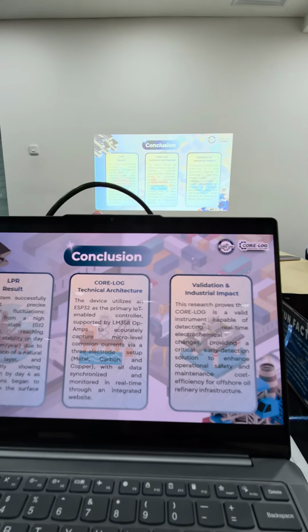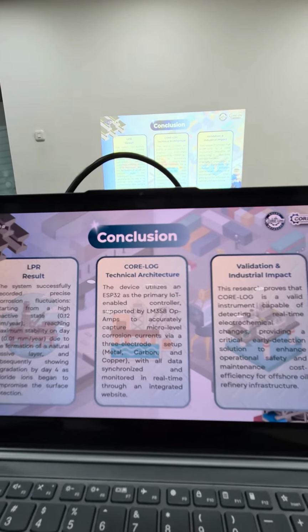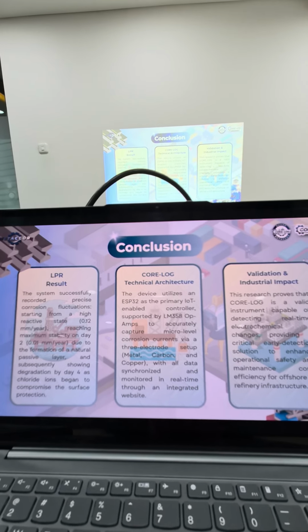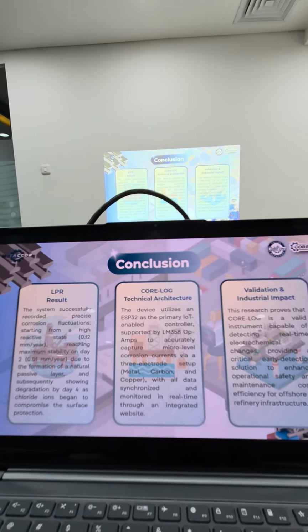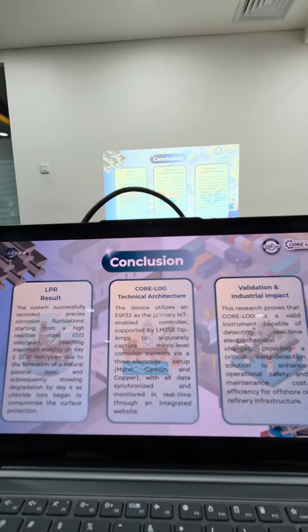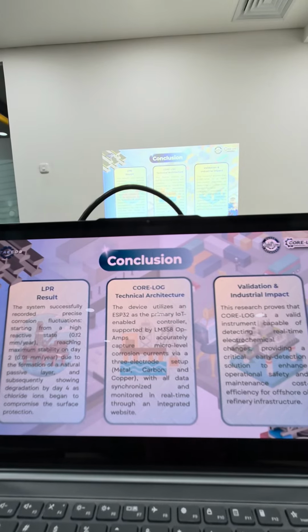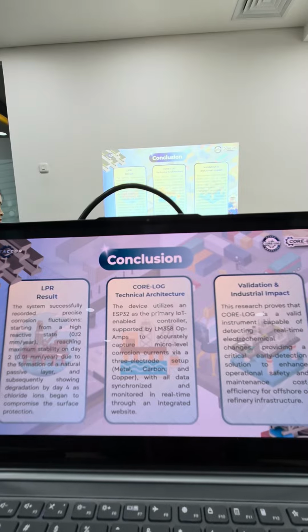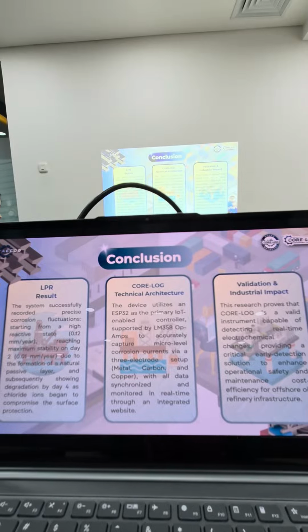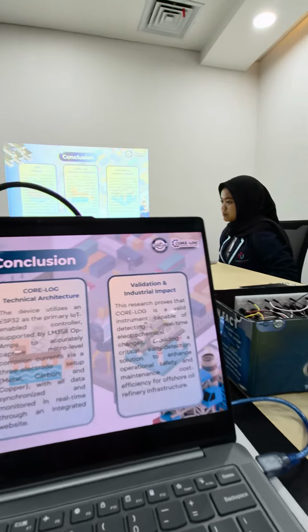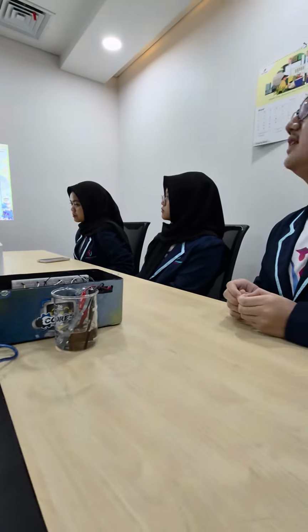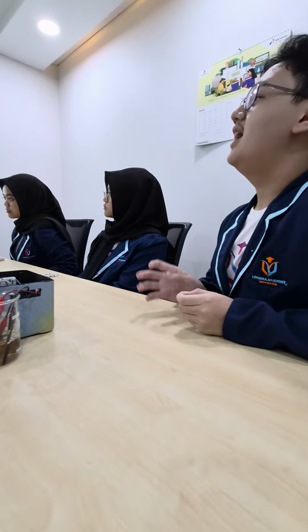The next one, we're going to talk about conclusions. The LPR results: the system successfully recorded precise corrosion fluctuations. As you know, our product has effectively checked the corrosion rate, reaching day 1 at reactive state 0.12 mm per year, as well as reaching the maximum stability on day 2 due to the formation of the protective layer. Until at the last day, by day 4, the chloride ions began to compromise the surface protection and break the protection itself.